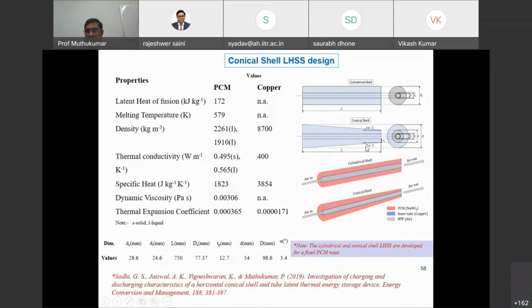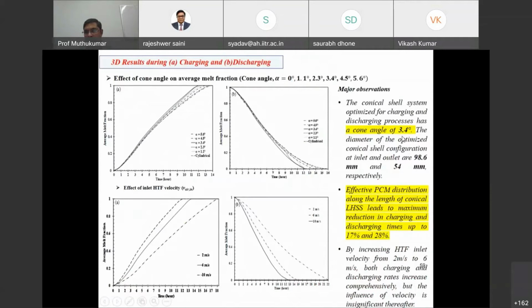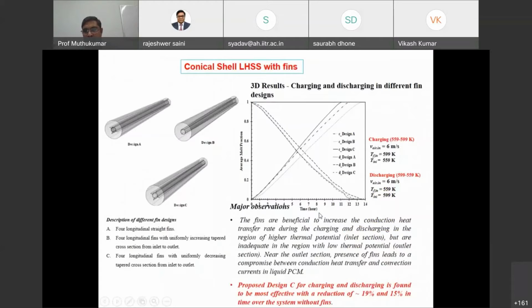Here we varied the taper angle from 1 to about 4 degrees, and then studied its effect, and we found that a taper angle of about 3.4 degrees provided better performance in terms of charging and discharging. When you maintain the taper angle of about 3.4 degrees, the charging and discharging times got reduced by about 17% and 28% respectively. So this is another interesting result. One can also have this kind of configuration for better heat transfer enhancement. And as usual, for the remaining things we vary the temperature, pressure, and all these things are possible.